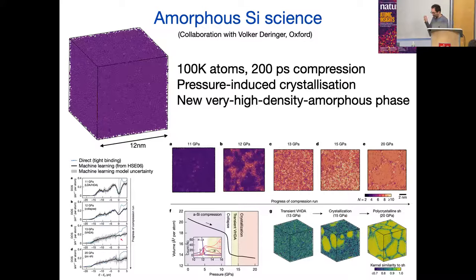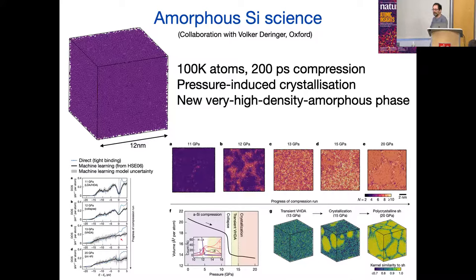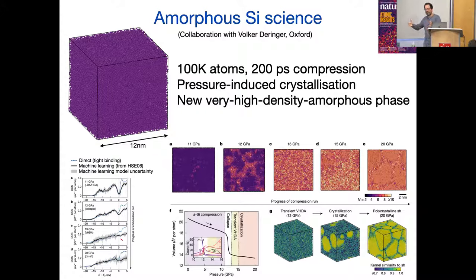Here's another example where we do new science. We do the same thing for silicon with similar parameters to carbon. Now we can study systems we couldn't before — amorphous silicon. What does it look like? There were no good models of amorphous silicon because it's not a crystal — you can't model it with just a few atoms. Using the machine-learned model that's a million times faster than electronic structure, we can make a 100,000-atom model of amorphous silicon.